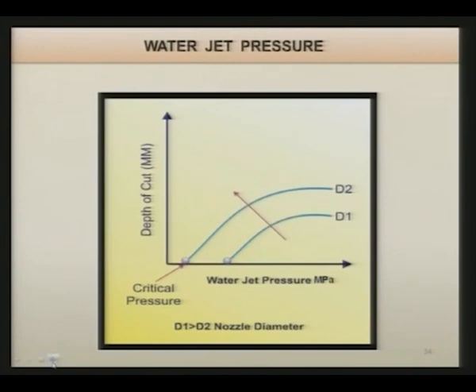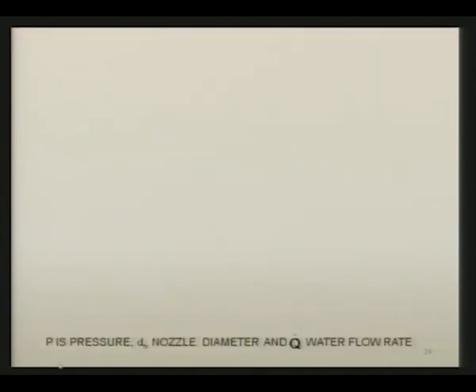Here it shows the effect of the water jet pressure on the depth of cut. It initially increases and afterwards it tries to stabilize. Now, you can also see the nozzle diameters D1 and D2. If the nozzle diameter is larger, then the depth of cut decreases. As you can see over here, it is because if the same power is there, then the pressure of the water or abrasive water jet coming out is smaller, and that is why the depth of cut is also smaller.